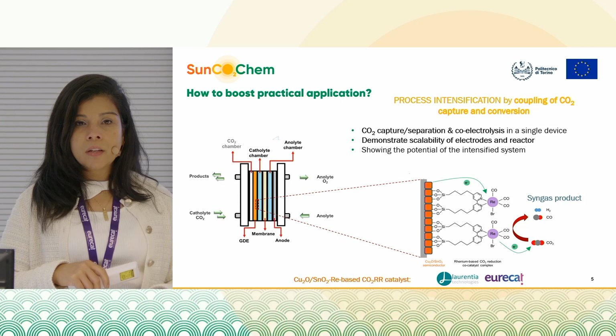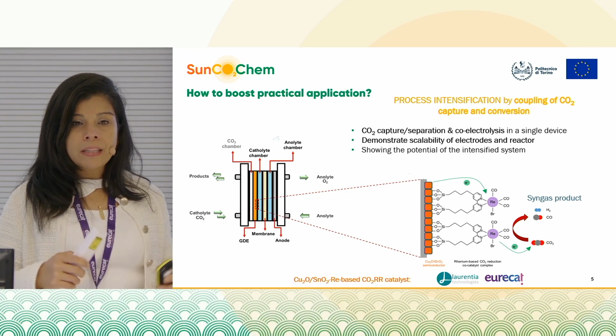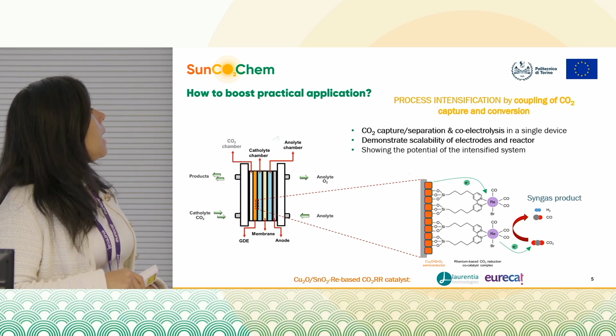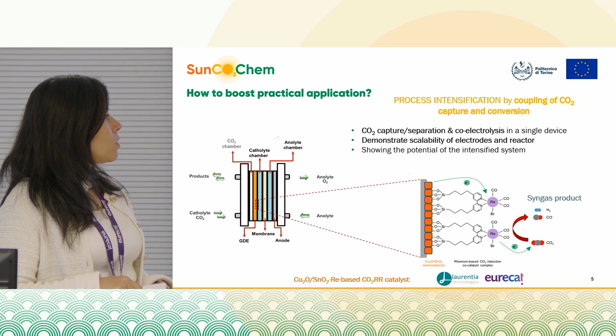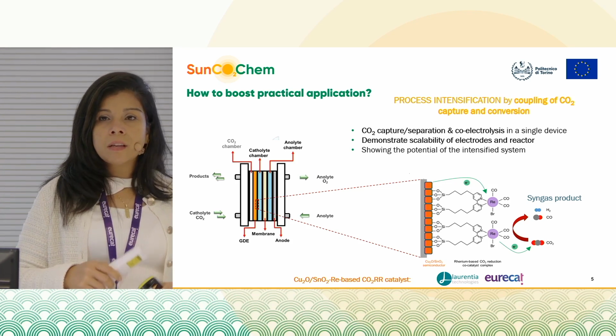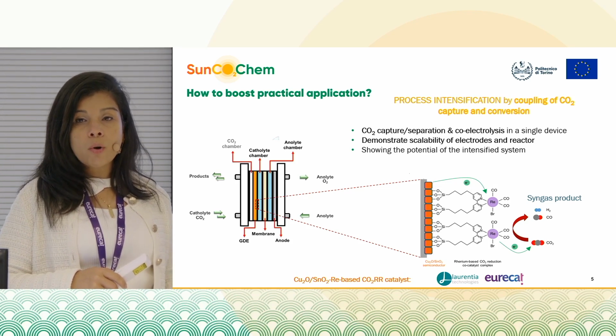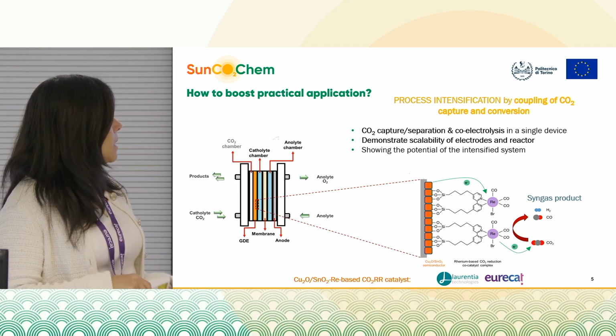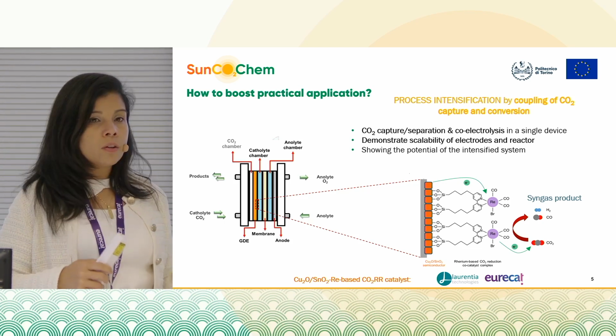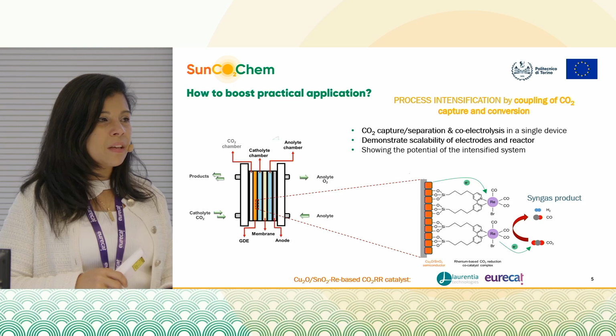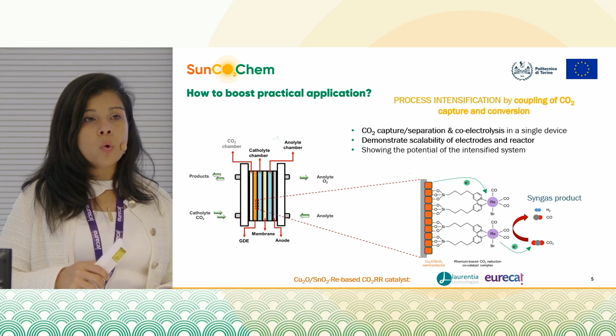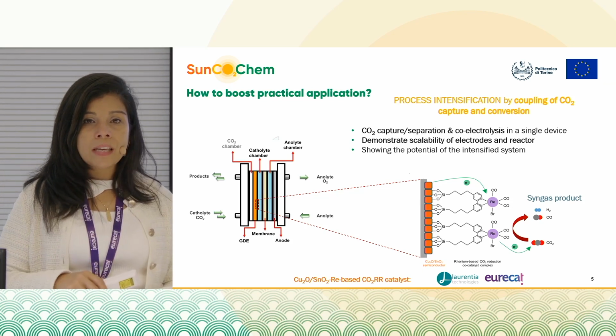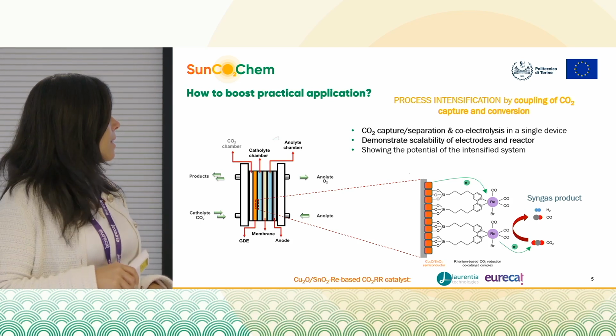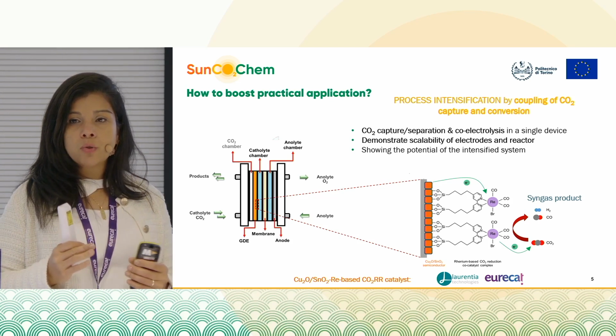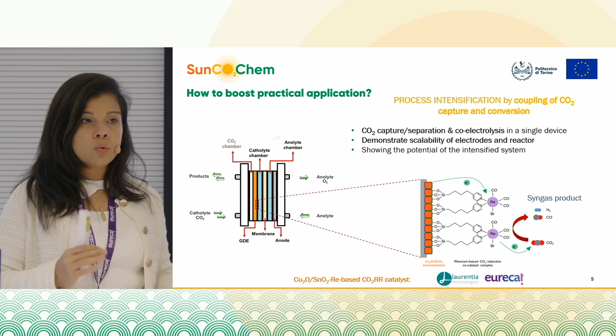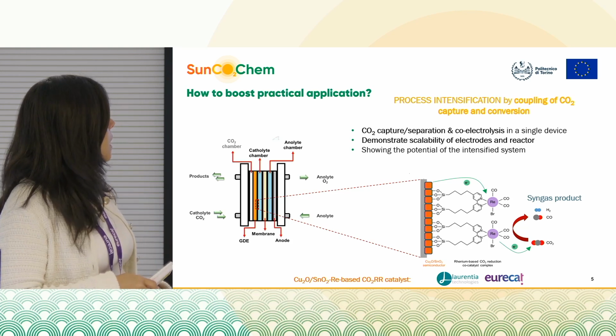copper oxide, tin oxide with some organometallic rhenium-based complex, aiming to convert CO2 to syngas, that is a mixture of carbon monoxide and hydrogen. And this is because, as you have seen and you will see in the next presentation, our goal is to do hydroformylation with this syngas mixture. And so the target was to obtain a syngas mixture of around CO to hydrogen 1:1 ratio.